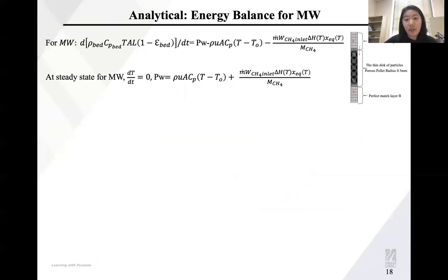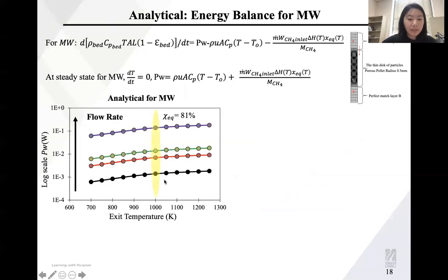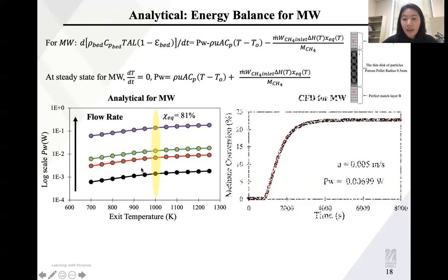And we did a similar analysis for the microwave heating. We calculate the energy balance, what kind of power input can drive this methane steam reforming reaction. And we found that we analytically solve this microwave heating at certain equilibrium conversion, that is the power input for each flow rate. And we also calculate at a certain flow rate, which is this point, the computational fluid dynamics gave us a much lower methane conversion as compared to the analytical simulations.